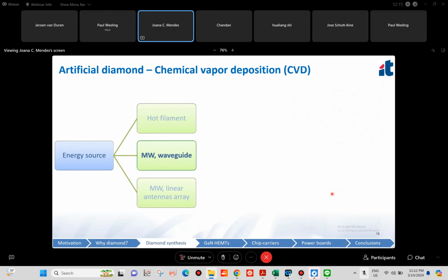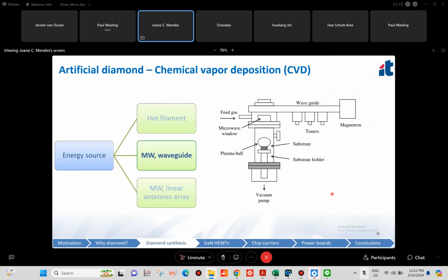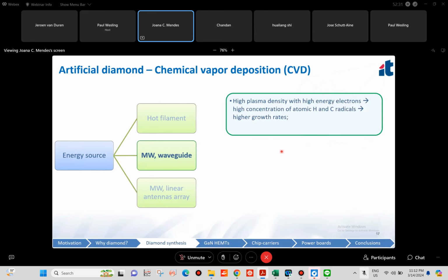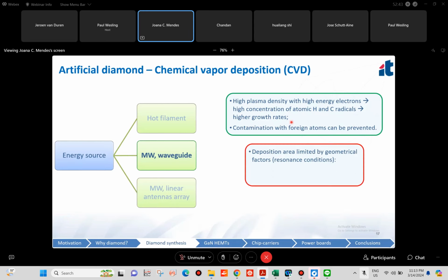But then we can also supply the energy as a microwave being generated here in a magnetron, and then the waves travel through the waveguide into the chamber, and they create a plasma ball. Well, it happens that this plasma has a very high density with high energy electrons. So we have a high concentration of atomic hydrogen and carbon radicals, we have higher growth rates, and we can prevent the contamination with foreign atoms. However, the deposition area is limited by geometrical factors. So we are typically limited to 4-inch if we use 2.45 gigahertz, or to 6-inch if we use 915 megahertz, even though these systems are a bit tricky.